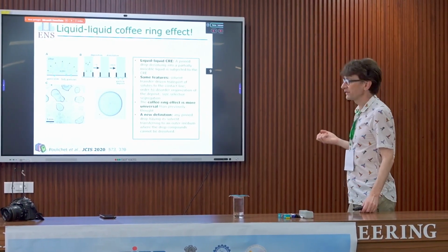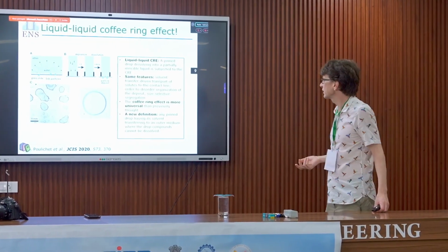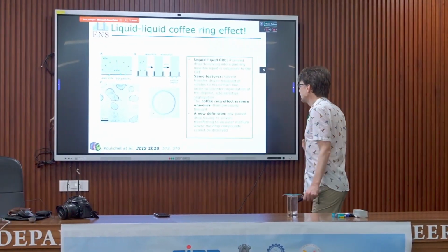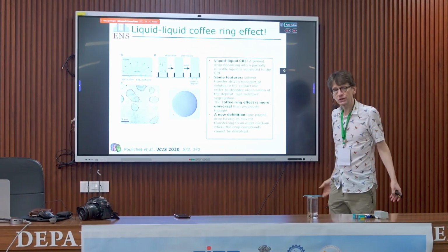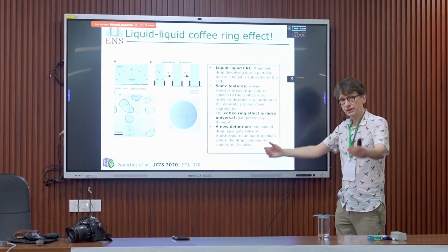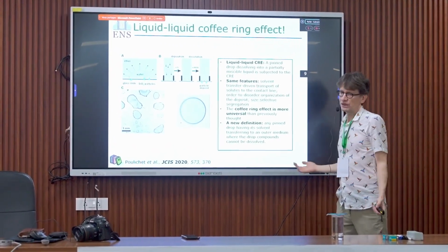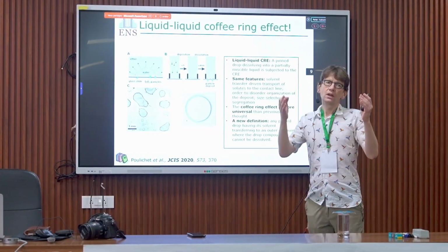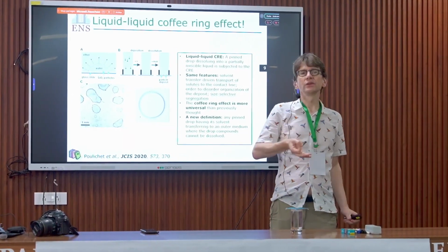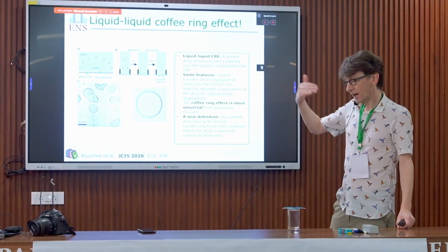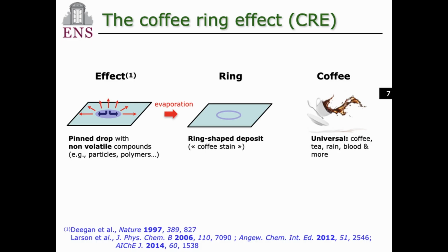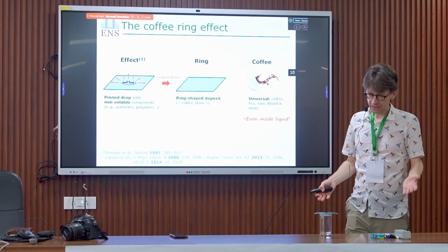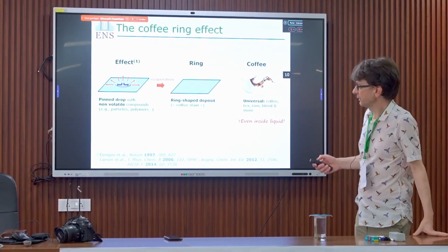So it shows that the coffee-ring effect is something even more general than we could think about. And I think as a new definition, you have to say that you don't need evaporation, you just need a transfer of solvent from the droplet to the outer medium. And as soon as you have contact line pinning, and as soon as you have solutes that don't dissolve in the outer medium, then you have the coffee-ring effect. Okay, so we see the coffee-ring effect is universal, it even occurs inside liquid, so you can have a liquid-liquid coffee-ring effect.